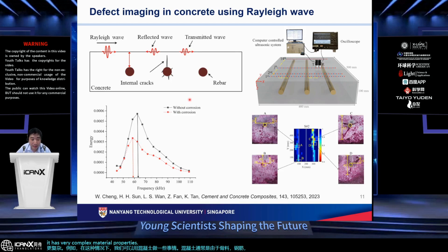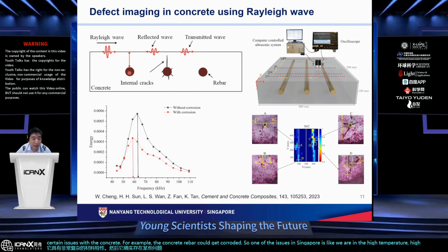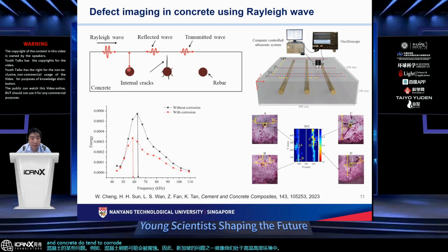And it does have certain issues. For example, the rebar in the concrete could get corroded. One of the issues in Singapore is that we are in a high temperature, high humidity environment, and the concrete does tend to corrode very fast. When the rebar starts to corrode, you will have rust growing around it. This rust will basically squeeze the concrete and you will form a crack, right? The crack will grow from the rebar and grow towards the surface.